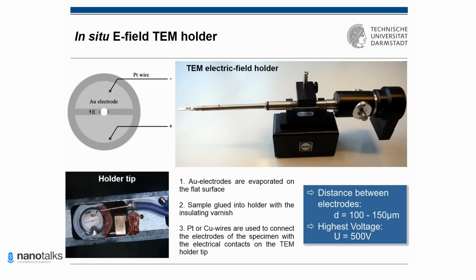Another challenge I would like to mention: in order to have a preferable orientation of our sample, we need a double tilt possibility. In our case, I didn't expect it, but our double tilt range was reduced due to these wires. Basically, you cannot tilt at a high angle, because otherwise the wire will become unglued and you will lose the contact, and you will need to stop the experiment. So the tilt was around plus minus 5 degrees, which was quite fine for my kind of experiments.